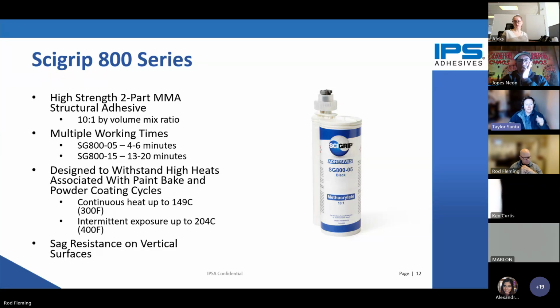Where this product really shines is it was designed to withstand high heats, especially heats associated with paint bake cycles and powder coating. So this product actually can take continuous heat to 149 degrees Celsius or 300 Fahrenheit, and then intermittent exposure, which we describe as 15 minutes, and then you can cool it down, and then 15 minutes again, up to 204 degrees Celsius or 400 Fahrenheit. And those are about the typical temperatures you see with paint bake and powder coat cycles.